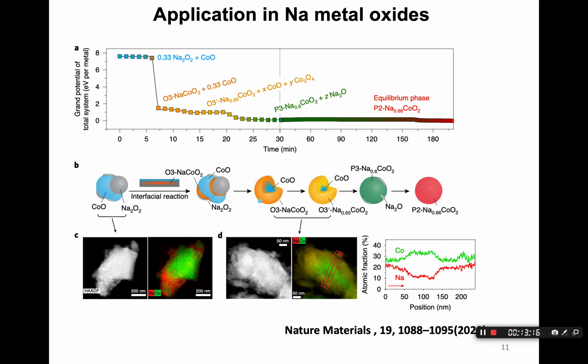So the grand potential basically tells you about the chemical potential, about the energy landscape of the reactions. It goes from top to bottom, but if you stop the heating in the middle, it is likely that you're going to stabilize those metastable phases. So this is what we can do to synthesize metastable promising functional materials.